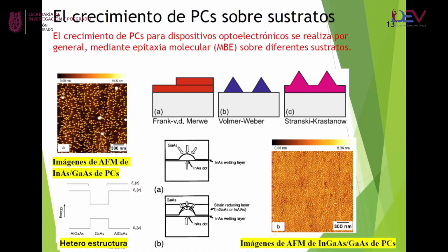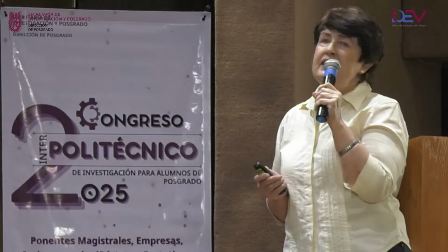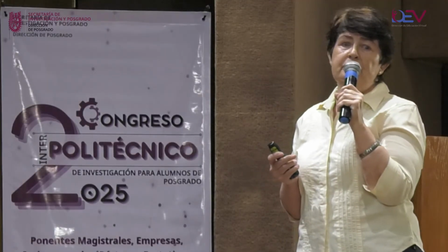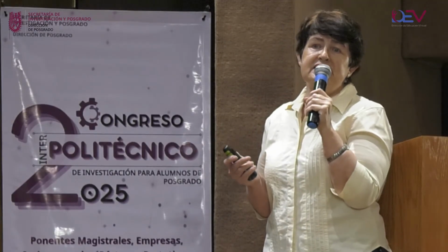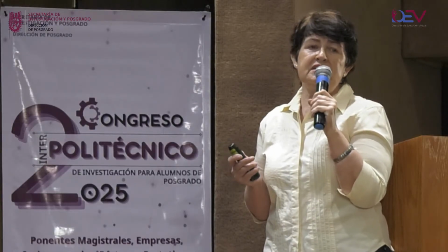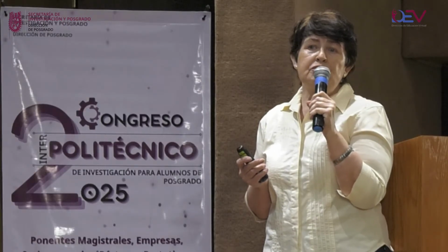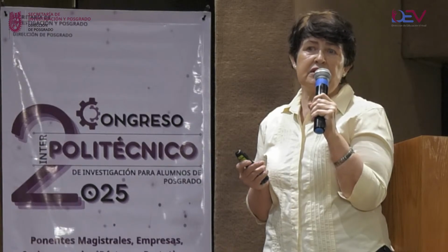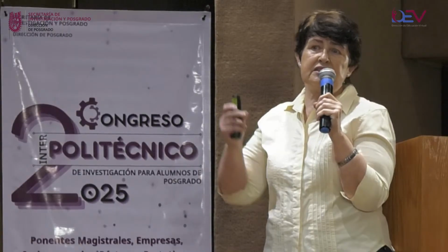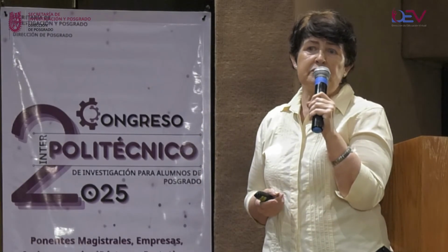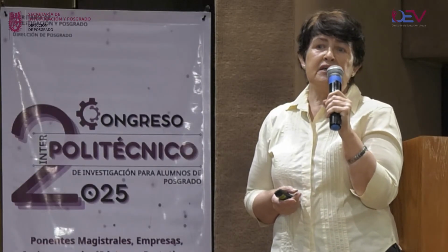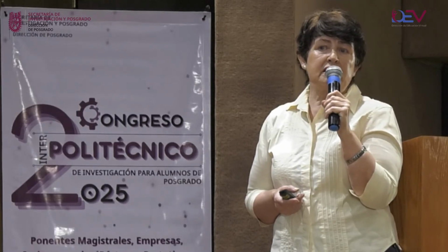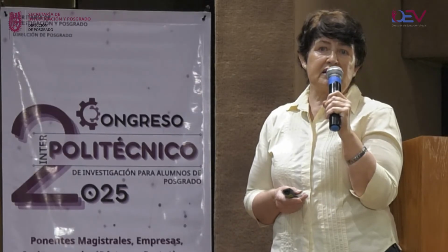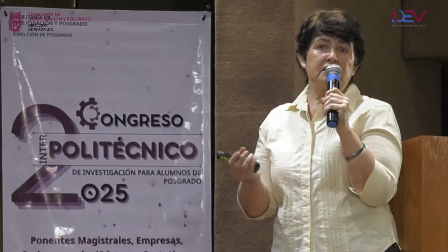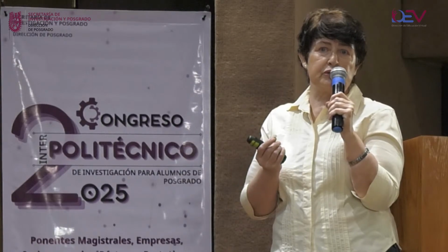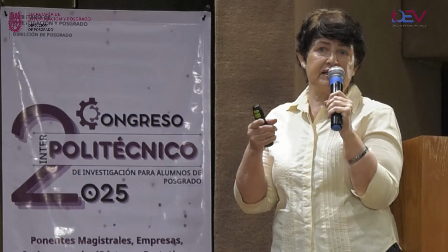Why do these quantum dots appear? We need to understand that the layer which should produce quantum dots has a crystal lattice parameter, and the substrate has a crystal lattice parameter nearly 7% different. Due to the mismatch, meaning a difference in crystal lattice parameters between two contacting layers, very great tension appears in the quantum dot material. Due to the relaxation, the layer which was originally flat generates quantum dots in the chamber in a very high level of vacuum.